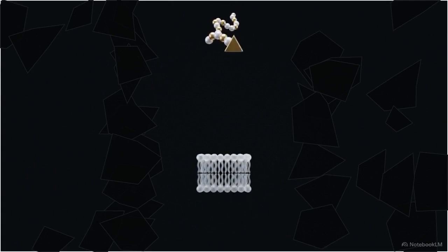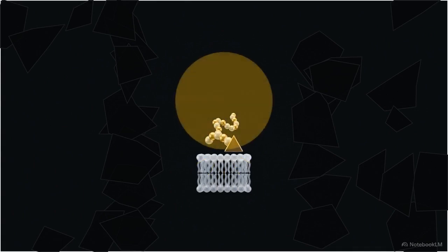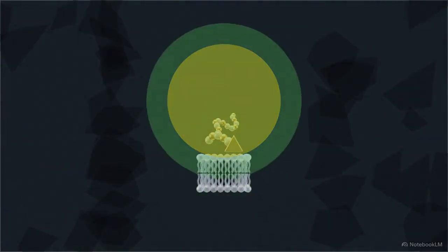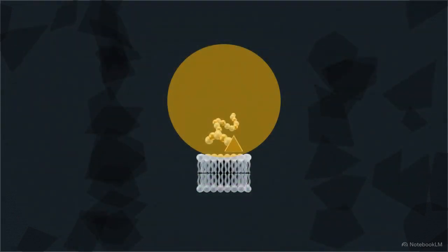This led to a molecular solution that bypasses gene targeting entirely, using cell membrane penetrating peptides paired with a bioactive IKVAV motif to physically anchor a regenerative signal to the lesion. This nanostructure physically embeds into a damaged lipid bilayer, anchoring the structure while leaving the bioactive IKVAV sequence exposed in the extracellular space. Anchored directly into the spinal lesion, the peptide provides a sustained regenerative signal derived from laminin.